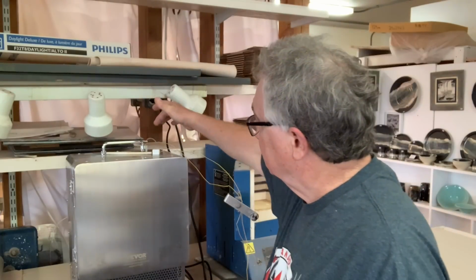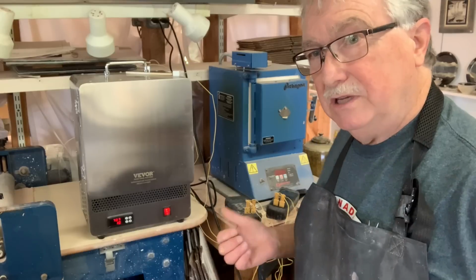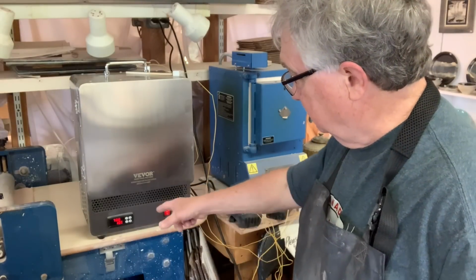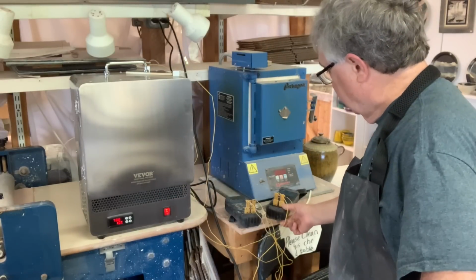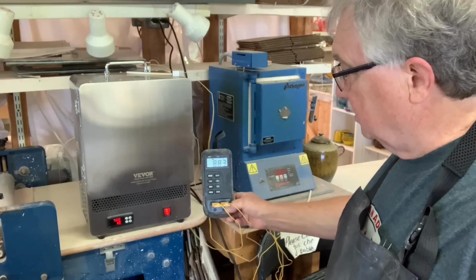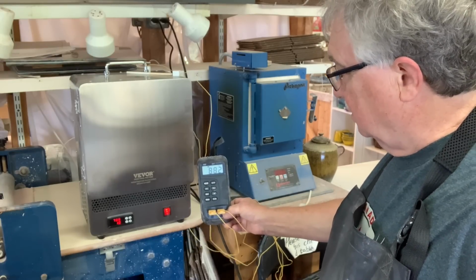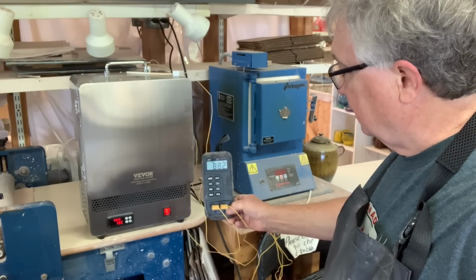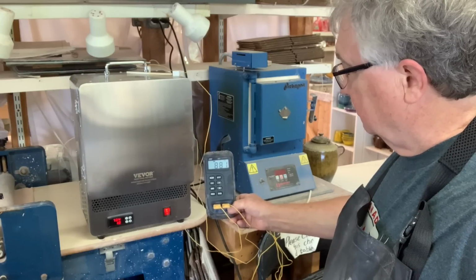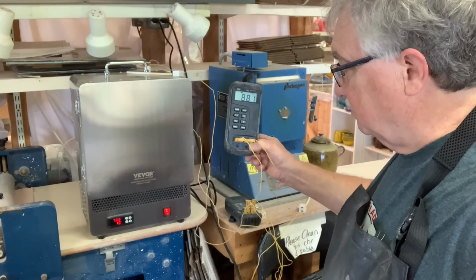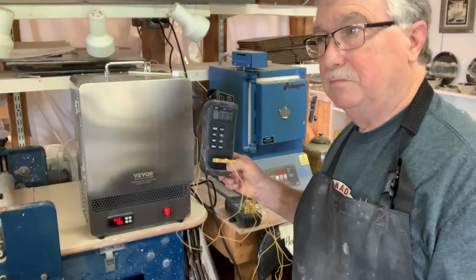So we've established that my pyrometer seems to be more accurate. This is a real Bisque firing now, just set the way the kiln is supposed to rise from the factory setting, which is too fast in my opinion, but we may be surprised. The reading was 100 degrees difference between this pyrometer and the one that I have here, and even now as it's cooling, I've got it going down to cooling, it's 795 in the machine and it's 882, 881 now on my pyrometer, which we double checked with another one to show they're both accurate.